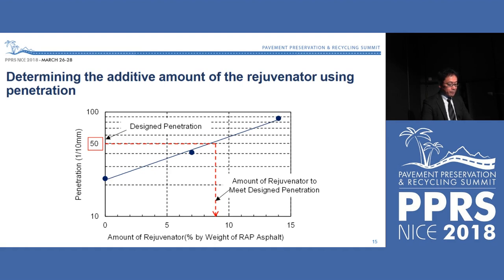What you see here is a way of determining the additive amount of rejuvenator using penetration. The mixing ratio of RAP and combined grading are determined, and the penetration of old asphalt recovered from RAP is measured. Then the penetration is obtained by changing the additive amount of rejuvenator added to old asphalt containing RAP. The relation between the additive amount of rejuvenator and penetration is obtained. The additive amount of rejuvenator which gives the designed penetration is determined. Afterward, the Marshall stability test is conducted on specimens to which new asphalt is added.